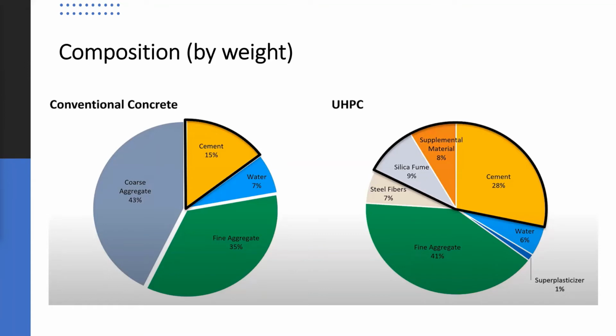What makes UHPC different? 75 to 80% of the ingredients of UHPC are the same as regular concrete: cement, sand, and water. It is the remaining 20 to 25% that makes the difference. The addition of silica fume and steel microfibers makes this concrete unique. These additions give the concrete a compressive strength of greater than 22,000 PSI, a tensile strength of about 900 PSI, and an elastic modulus of 6 million PSI.